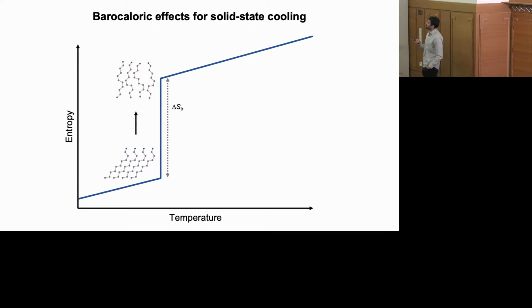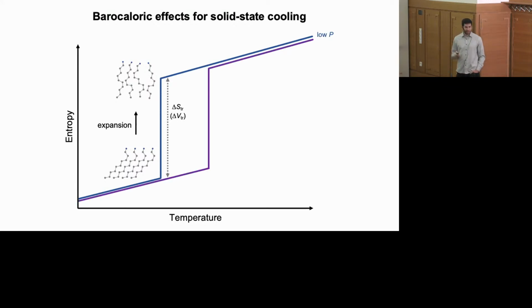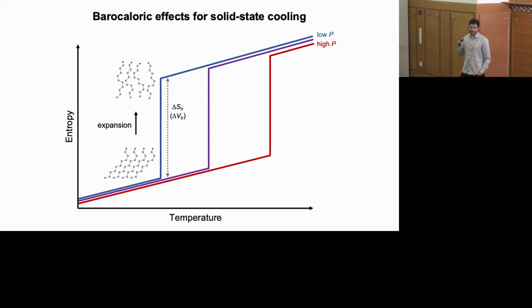Because if you have a material that undergoes this type of transition, these types of order-disorder transitions are often associated with large volume changes. Typically, as you go from an ordered low entropy state to a more disordered state, this involves an expansion or increase in volume. And so if you imagine starting to apply pressure to a material, so hydrostatic uniform pressure around the material, as you start applying pressure, you're going to be favoring the more compacted ordered phase. So you're going to be shifting the phase transition temperature to higher and higher values as you start applying pressure.